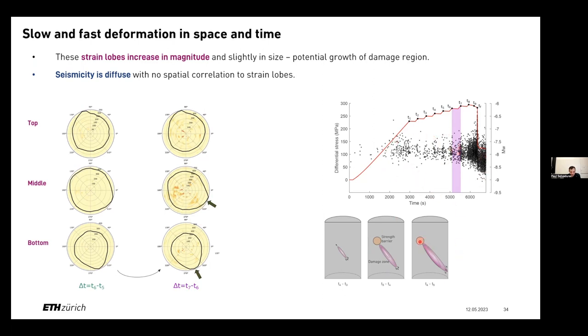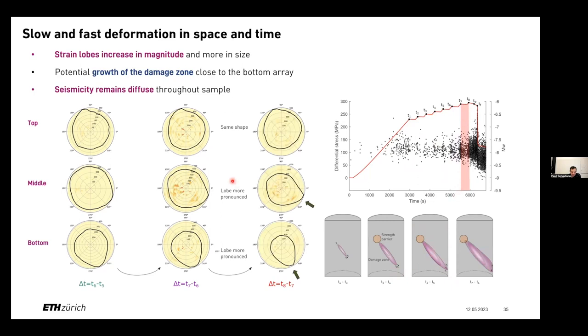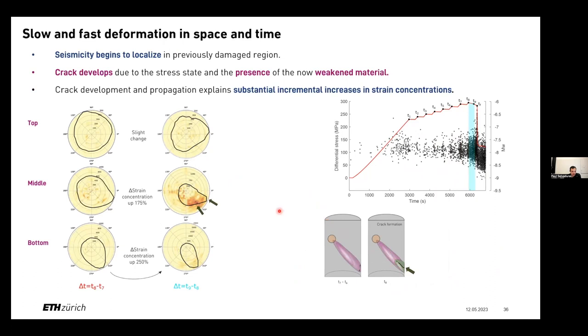The hypothesis is that the damage started in the middle of the sample at a weaker point and moved downwards, possibly inhibited by a strength barrier in the up-dip direction. And then once it reached the edge, where the strain lobes are really localized in the surface measurements here, we started to produce a crack within the damaged region that now produced quite a significant amount of localized seismicity. We see that the strain started to have large jumps in concentration between small time frames here. So we're looking here between each time frame, T8, T7.